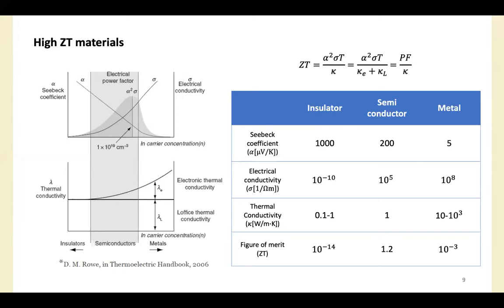Then which materials have high ZT value? This is a comparison of three big different materials groups: insulators, semiconductors, and metals. We can see the tendency of each parameter on the left-hand side. For example, higher value of Seebeck coefficient in insulator, whereas higher electrical conductivity in metal. So after calculating these values, we can recognize that semiconductors have the highest ZT value. We should keep in mind that it is very difficult to satisfy high ZT value because these three physical properties are interdependent. In other words, a modification to any of these properties often adversely affects the other properties.